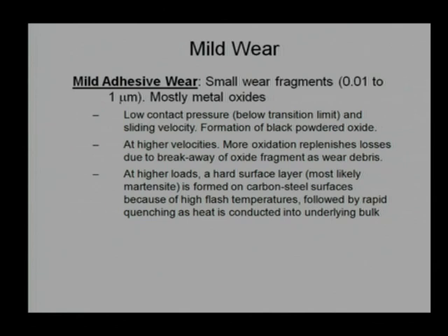is in the mild domain, or maybe say ultra mild also. When the wear particle size is almost 10 nanometer, we do not count that as wear; it is ultra mild wear. However, if it is roughly 1 micron in volume size, we know the major part will be the oxide. So, the material removal rate as such is not very dominant. That is tolerable if you are trying to design a component for 5 years, 7 years; this kind of mild domain will work very well.